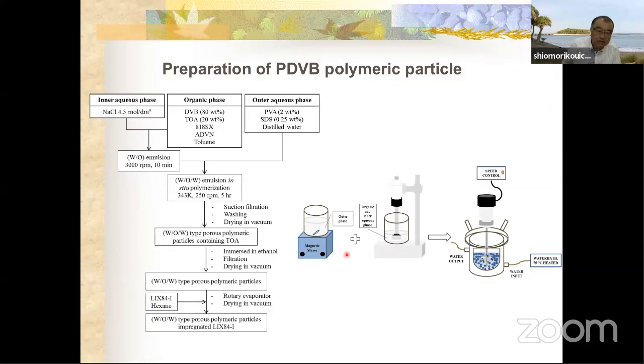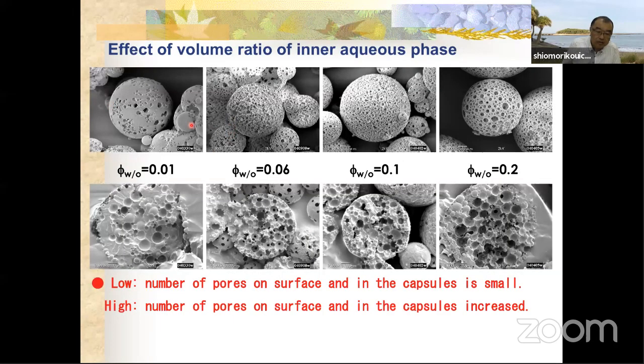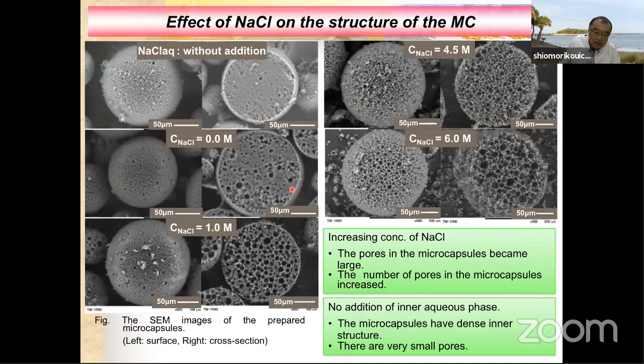When we change the ratio of the organic phase and the aqueous phase, we can change the porosity of the particle like this. When we add a large amount of inner aqueous phase, we can make a quite highly porous particle like this. And also the concentration of the sodium chloride in the aqueous phase was changed. So the pore diameter can also change depending on the concentration of sodium chloride like this. When we select a high concentration in the inner aqueous phase, we can make a quite highly porous particle like this.